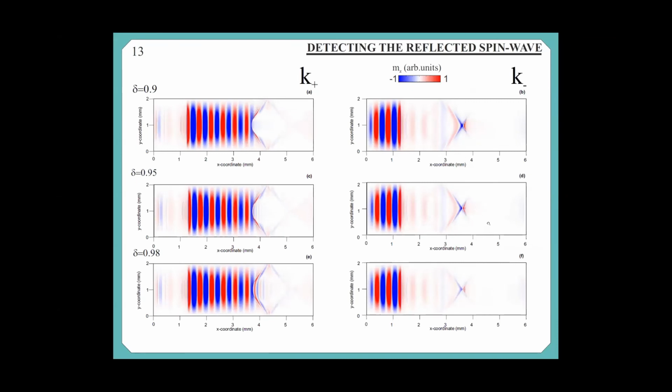In order to explain the phase change, a magnetic simulation was performed in which the magnitude of heating was changed, leading to a change in the saturation magnetization of the YIG film. And we have propagation waves with positive wave number and negative wave number. It can be seen that a reflected wave arises from the heating area, which has increased amplitude with the given parameters when the heating changes.